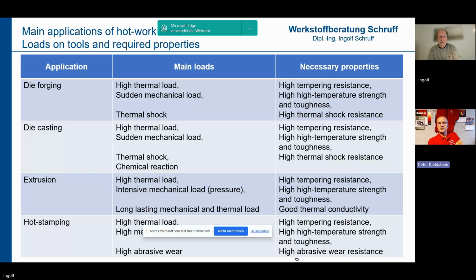And don't you have wear on the die at the inlet area, because the velocity of the liquid must be pretty high? It is. I heard a value that says velocity can be locally up to 70, 80 meters per second. Wow. That is really fast. Yeah, you need to fill the die very rapidly. Otherwise, you will start solidifying the aluminum before it is completely filled.